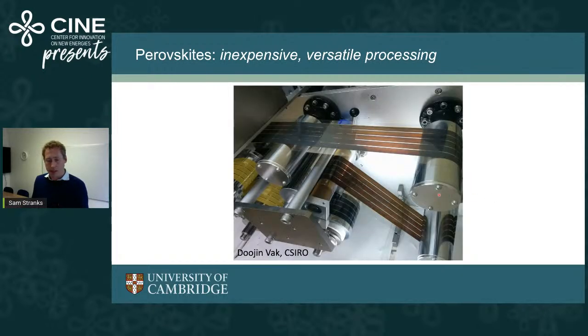And because they can be processed at low temperature, and I say low temperature because it's low temperature for semiconductor processing, 100 degrees Celsius or 150 degrees Celsius is very low. This means we can process on different substrates than typical semiconductor materials. So one can think about processing on plastics or metal foils. And this is an example of a prototype roll-to-roll processor where the perovskite is processed on the plastic.